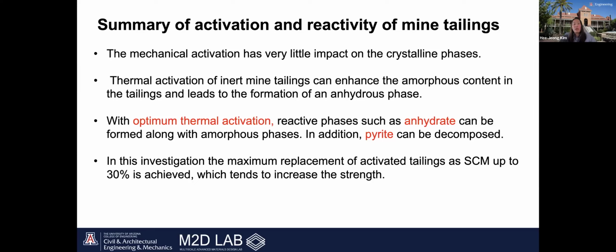And we also found that up to 30% of cement can be replaced with activated tailings without losing strength. In fact, the strength improves, and this approach supports the sustainable use of mining waste in construction materials.